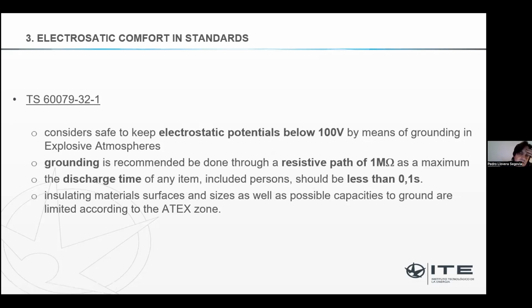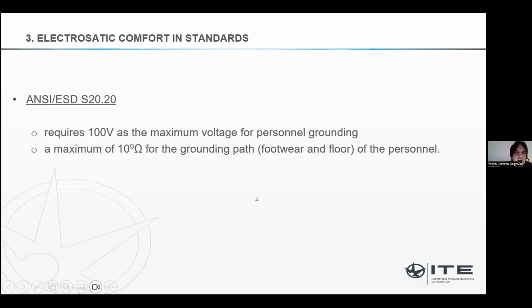60079-32-1. Okay, this is for ATEX zones. So again, electrostatic potential should be controlled below 100 volts. Grounding with a resistive path of 1 megaohm. Discharge time of less than 0.1 seconds. That's too fast for electrostatic comfort. I think some seconds could be enough for electrostatic comfort.